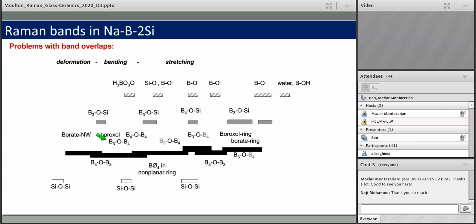If you can get the Raman on it, you can get a spectrum and identify it. If, on the other hand, you have a ceramic that is not so translucent and you don't have any phase contrast, you can't identify the phase optically, for instance, the next best way is to do a Raman map. You look at the intensity of a peak or a series of peaks, and you raster point by point over the sample.